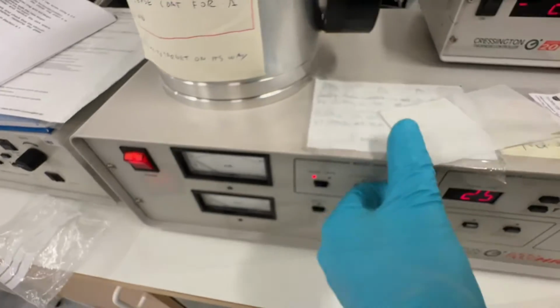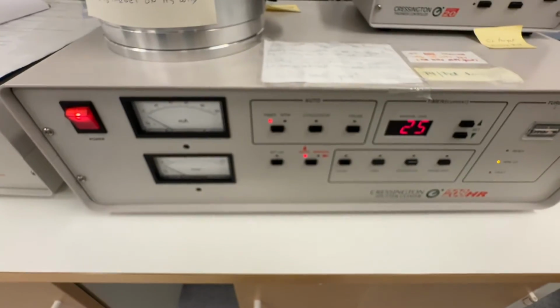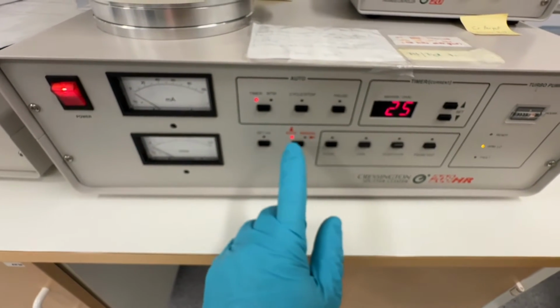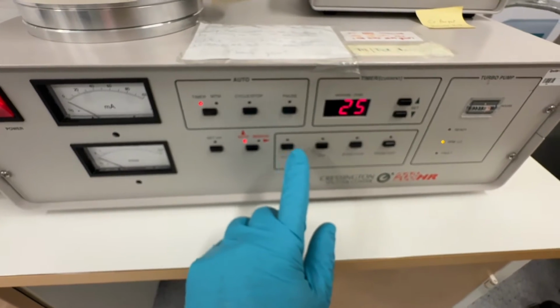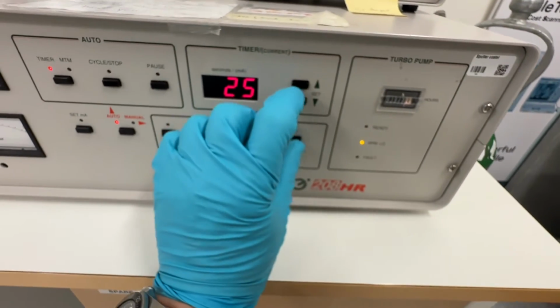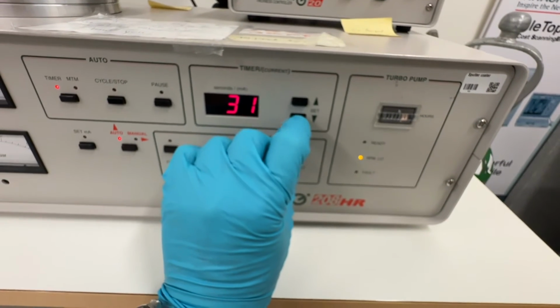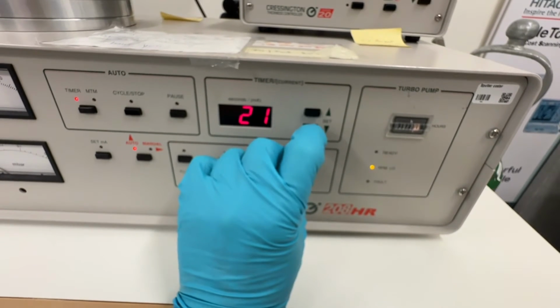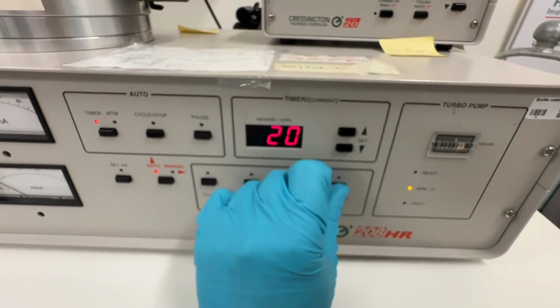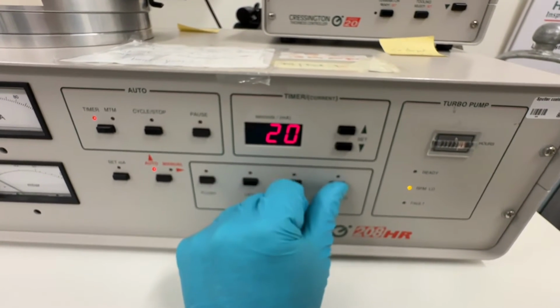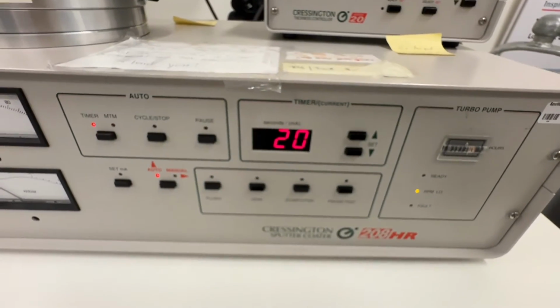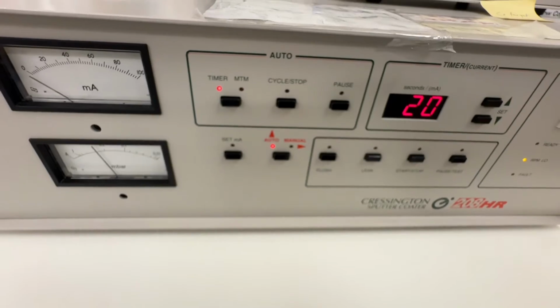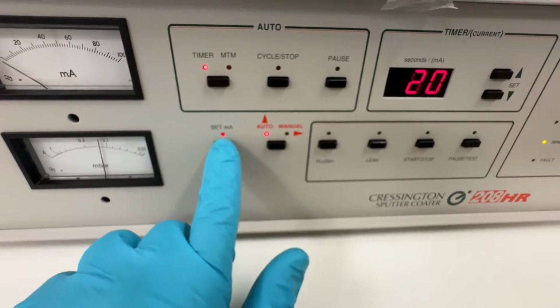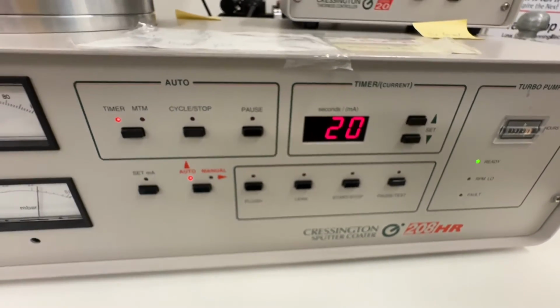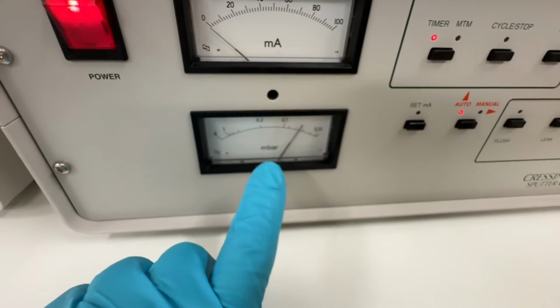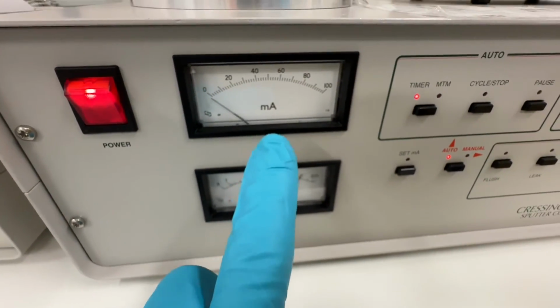Sputter was turned on, and since we used the chrome target previously, we're going to change the timer, the set time. We have the timer set to 25 seconds here. So somebody has been here changing the timer from the 300 seconds, which usually is used for the chrome target. We only need 20 seconds for the platinum palladium target, and it's set to timer over here. You can see here that we're sputtering at 80 milliamps. Here you see the pressure in the chamber, and here you see the milliamps.